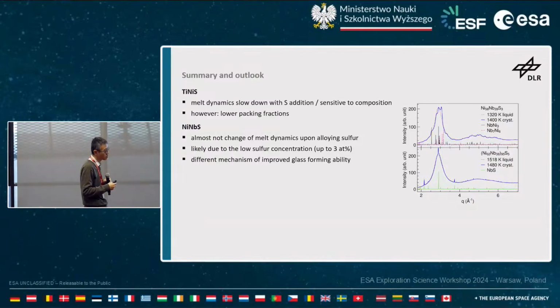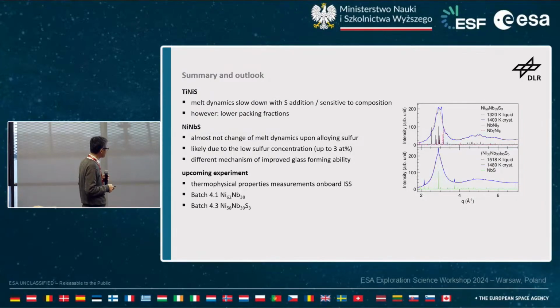We have already done a first solidification experiment with levitation. One can see that the primary phase forming from the undercooled liquid is changing as a function of sulfur content. That's why we are starting to understand what kind of role sulfur is playing. The upcoming experiment on board the space station, we are very happy that we can be involved from our side, on this binary alloy, because we are also interested in the binary alloy properties as a comparison. And batch 4.3 will then study the sulfur-containing alloys, both viscosity and other properties.